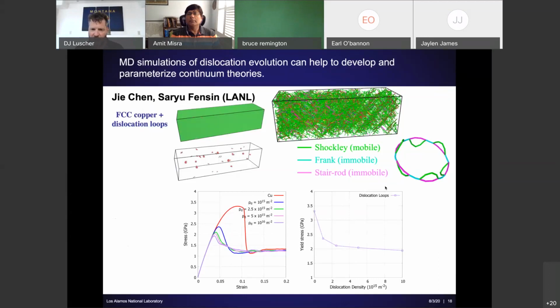Of course, that's a highly over-idealized situation. The reality is you have a distribution of mobilities of dislocations from zero, which is trapped in some kind of debris, and able to travel at some sort of unencumbered velocity, and there's actually a distribution between those end states. So the concept of mobile and immobile dislocations is somewhat a modeling construct to explain the competition, but I think it's a lot more complicated in reality. But you could just imagine the local environment in this mess. Some dislocations will be able to move without being tangled, and other ones are stuck.